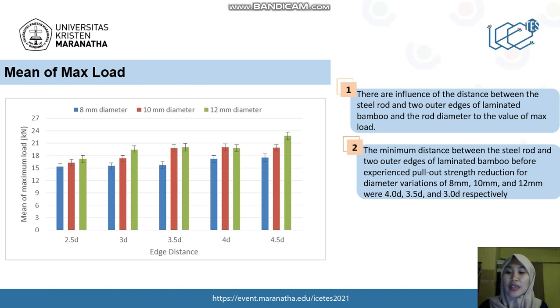This is the chart of edge distance and mean of maximum load relationship. From the chart, there is influence of the distance between the steel rod and two outer edges of laminated bamboo and the rod diameter on the value of maximum load. The explanation: at the same diameter, the greater the edge distance, the greater the mean of maximum load. And the minimum distance between the steel rod and two outer edges of laminated bamboo before experiencing pull-out strength reduction for diameter 8 mm, 10 mm, and 12 mm were 4 times D, 3.5 times D, and 3 times D respectively.